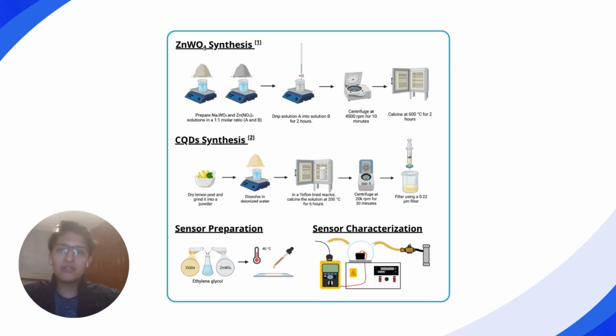For the sensor preparation, both the zinc tungstate and the carbon quantum dots were mixed in an ethylene glycol solution at around 40 degrees Celsius. Once the solution looked homogeneous, using a pipette, 5 layers were deposited in the glass substrate. The same procedure was followed for pure zinc tungstate and carbon quantum dot sensors.